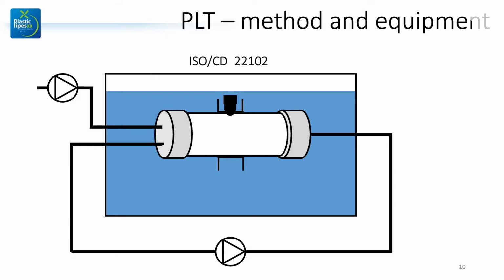Now in this case, it will just take too long to fill it like this. The temperature isn't enough to accelerate the test properly. So we need the detergent again. But in this case, the tensile stresses due to the point load come from the inside. So therefore we need that circulation pump again. And that will distribute the detergent through the pipe. And then we have detergent inside the pipe in this case.